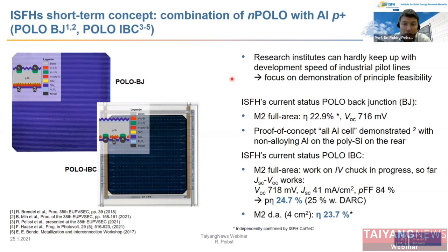So we can hardly keep up with the optimization of the devices, but we can only focus on the demonstration of principal feasibility. And this is what we have done for the POLO back junction cell and for the POLO IBC cell. For the POLO back junction cell, I would say our efficiency so far is fair. The VOC values are already promising, and we think we can increase the efficiency quite soon to higher levels.